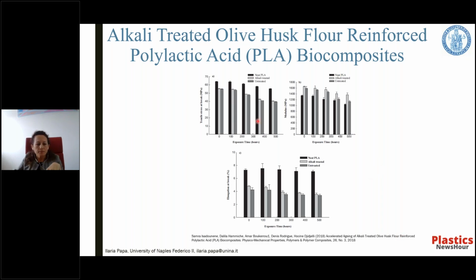Finally, the samples were subjected to tensile tests also in this research, and it was observed that the PLA with olive flour, or OHF, compound showed an increase in the Young's modulus, and in particular, the treated samples show this increase. Following the aging process, there is a deterioration of the mechanical properties of the samples, but it is observed that the treated samples have a better behavior and therefore a lower loss of mechanical strength compared to the untreated samples.